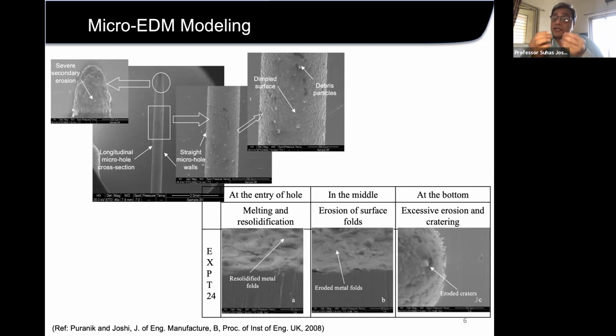And these particles, when they try to come out, actually get trapped between the electrode and the surface, and they generate different sparks at different places. But yes, though we get secondary eroded surfaces, that secondary erosion is very prominent at the ends of the electrode. Now what happens is that towards the tip of the electrode, these debris particles actually eat away the electrode itself, because of the sparking process.